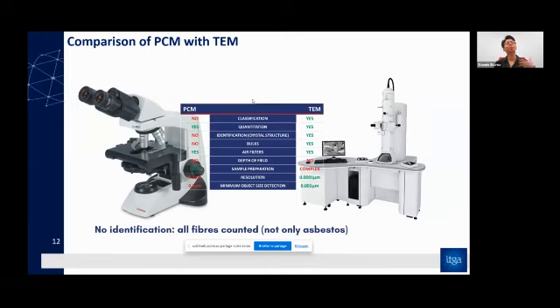Now moving on to phase contrast microscopy, which is another type of optical microscope. In this case, we can classify, we can quantify. However, the identification is a problem. It detects all types of fibers, but we are not sure whether it's asbestos or not. It can be another refractory fiber. The sample preparation is easy compared to, of course, TEM. For both PCM and PLM, the sample preparation is super easy compared to TEM. However, there are these limitations in terms of size, quantification, and identification.